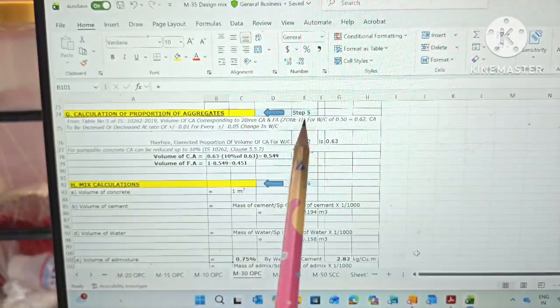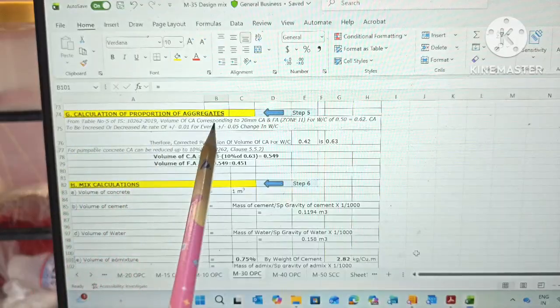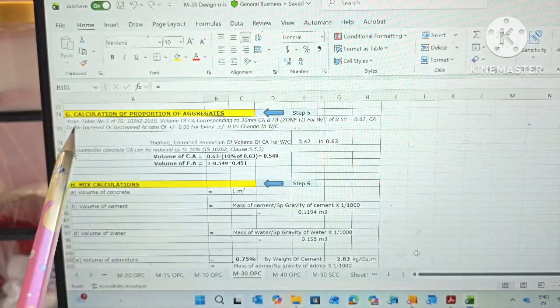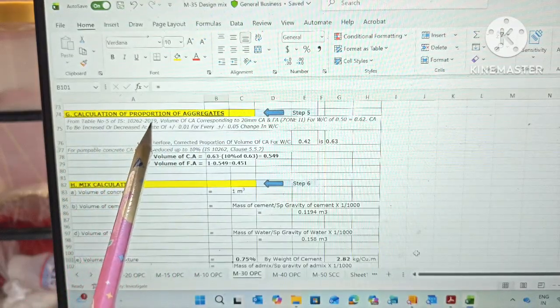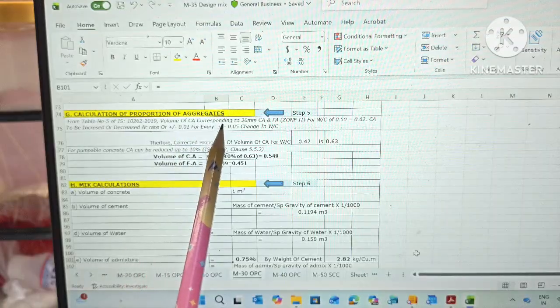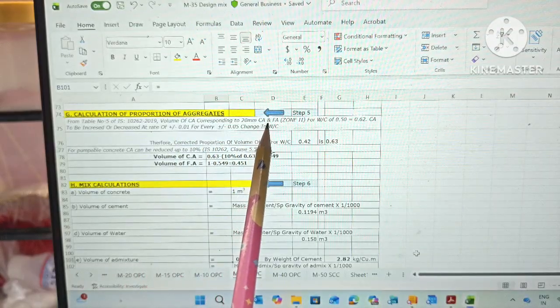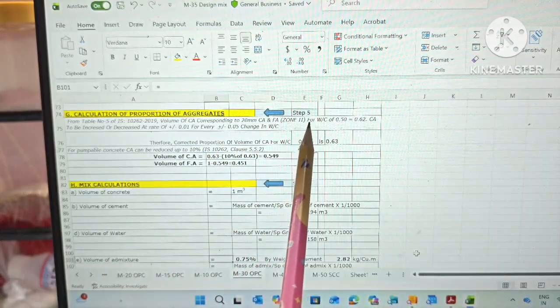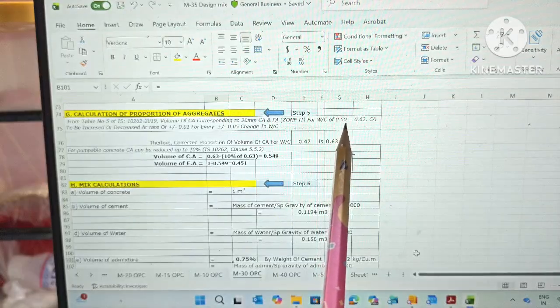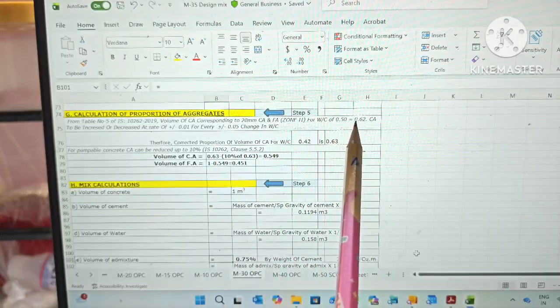Now moving to step number 5, that is calculation of proportion of aggregates. Friends, from Table number 5 of IS 10262:2019, the volume of coarse aggregate corresponding to 20 mm coarse aggregate and fine aggregate of Zone 2 for a water cement ratio of 0.5 is 0.62.